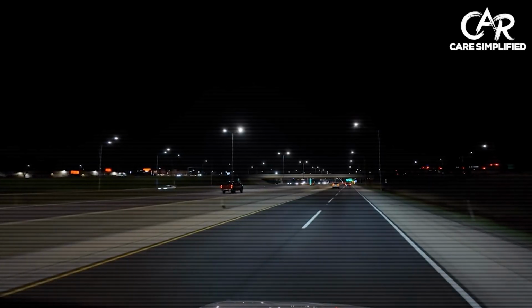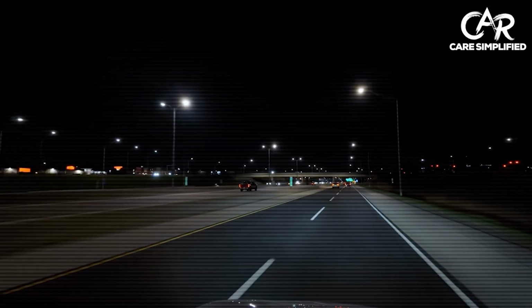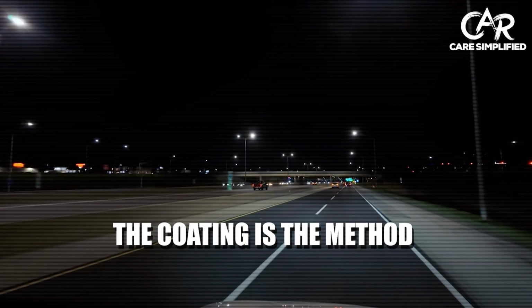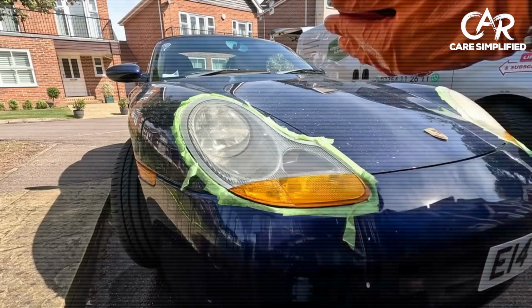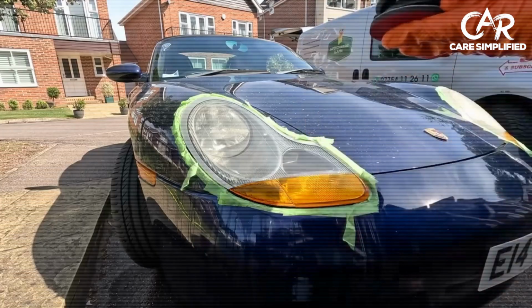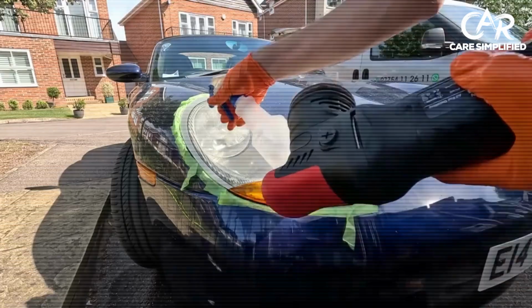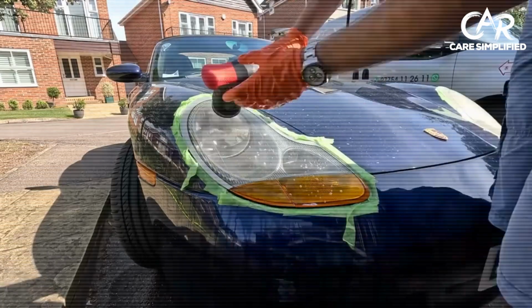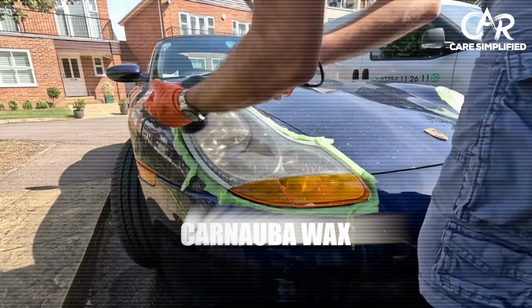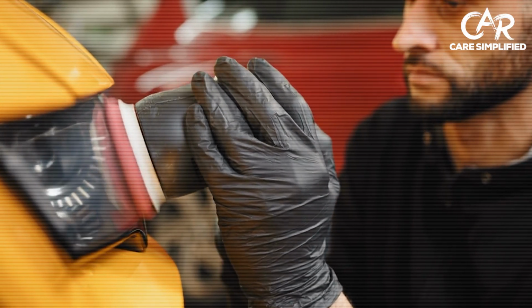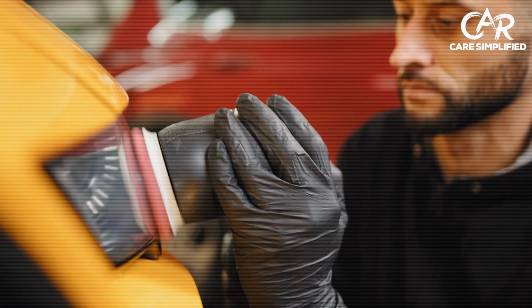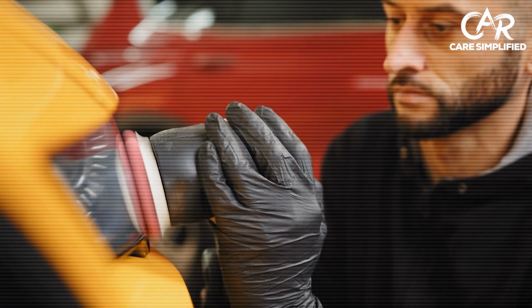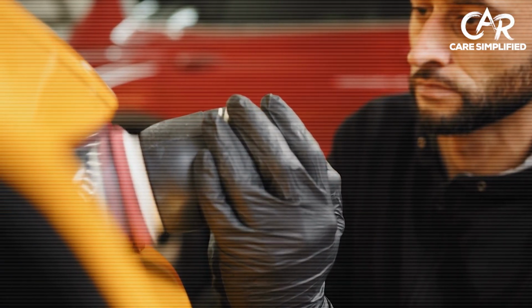Japanese car care approaches this differently. The coating is not an afterthought. The coating is the method. Sanding is just preparation, and the level of coating you choose determines how long your results last. Level 1 is a polymer sealant or carnauba wax. Easy to apply, inexpensive, but it acts as a sacrificial layer that wears away within 3 to 6 months. Good for a quick fix, not a long-term solution.